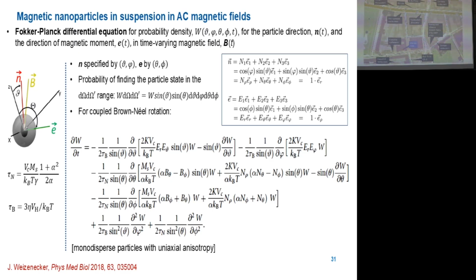This is a good question. If the particles are, for example, coated with some material, if they are stabilized, then there should be basically no difference between the dispersed state in the suspension and the dry state without the solvent, because still the particles will be separated by the coating, by maybe some diamagnetic stuff, so they will be separated and there will be no additional effect of dipole interparticle interactions.